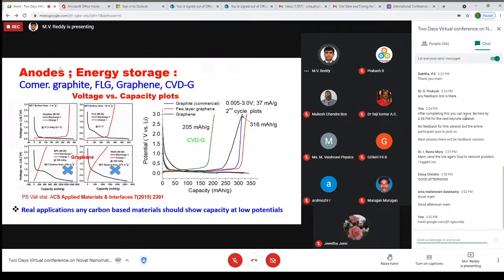nanomaterials. People are using graphite because of the good charge discharge potentials at the lower potential. Again, we look into graphene, graphene, etc. Although we get high capacity, the problem is these materials may not be really promising. Only graphite is a little bit good because of the lower potential. As a layman, in any research you do, always look for the reversibility after the first cycle. For any good material, getting a capacity at the lower potential is very important.